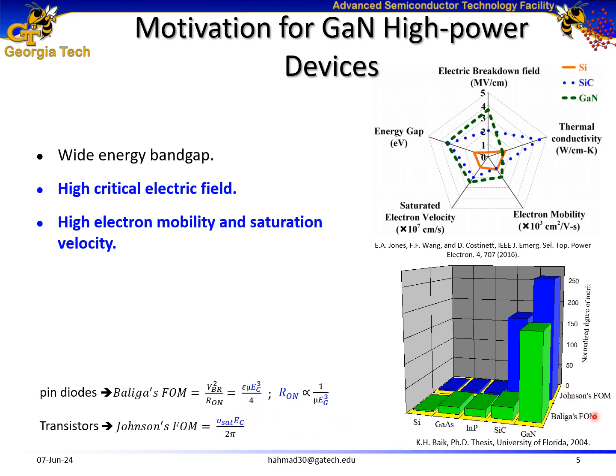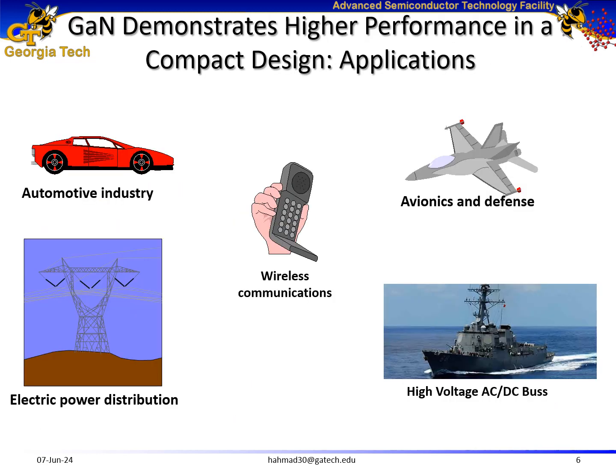So, in terms of both figures of merit, for pin diodes and for transistors, gallium nitride has higher figures of merit as compared to the other semiconductor materials. Also, the figure of merit for pin diodes is inversely proportional to the on resistance, which is dependent on the band gap of the material. The higher the band gap, the lower the on resistance, and the higher the breakdown voltage, which is another motivation for my study of pursuing gallium nitride based pin diodes. Due to the compact size of gallium nitride, its applications range from commercial to avionics and defense.